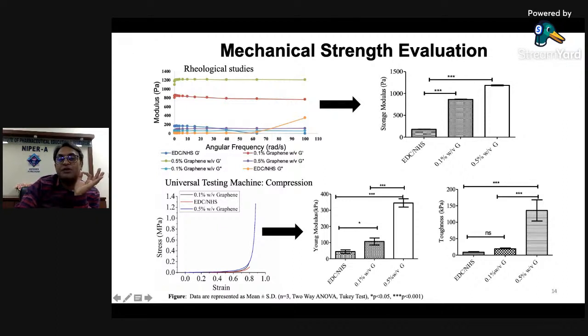So overall, the Young's modulus, which actually represents the sponginess and compressiveness of the material, shows that 0.5% is highly compressive and very spongy-like material compared to EDC-NHS and the other graphene concentration.